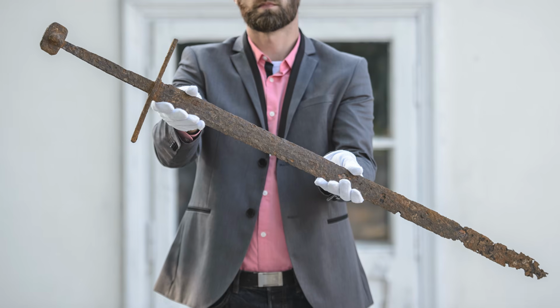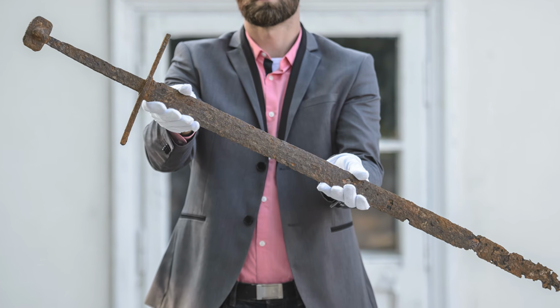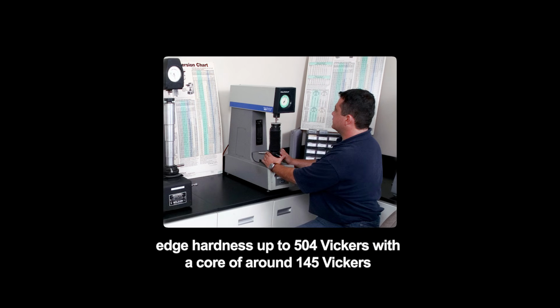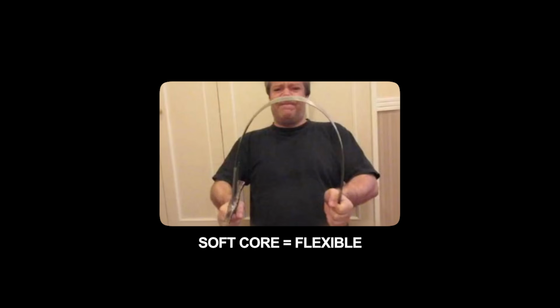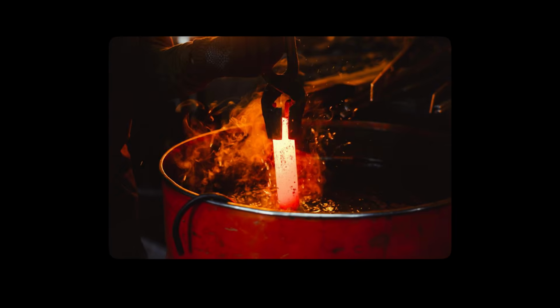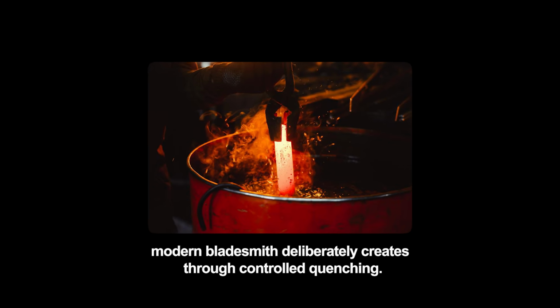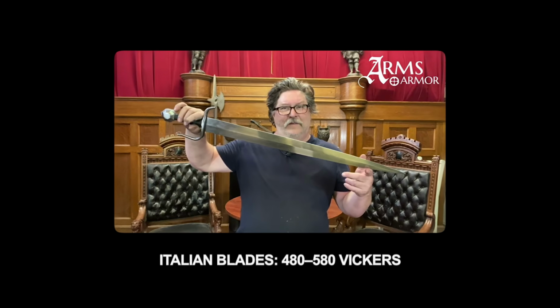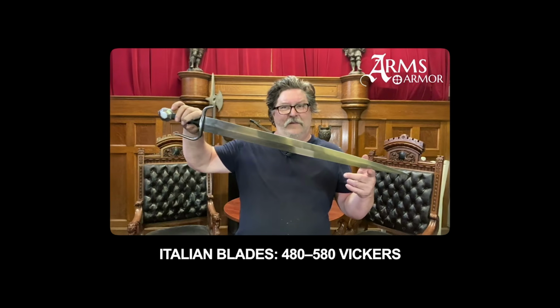A 15th century Polish sword from Raciborz tested at edge hardness up to 504 Vickers with a core of around 145 Vickers. The core is essentially soft iron, tough, flexible, resistant to catastrophic fracture. The edge is hard martensite, the same crystalline steel structure a modern bladesmith deliberately creates through controlled quenching. Renaissance blades from Brescia in Italy showed edge hardness between 480 and 580 Vickers across multiple specimens.